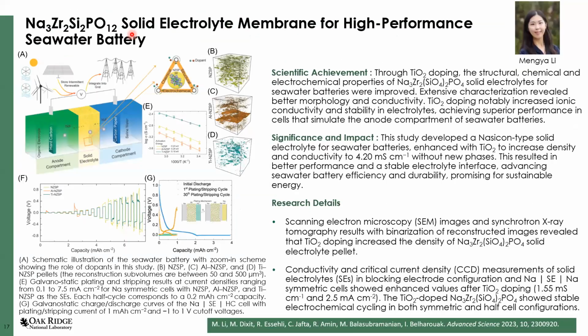So solid state materials are used in other things. In our group, we have small projects on long duration energy storage. This is an example of work where seawater is used on one side of the compartment and an organic electrolyte on the other side. By using this, one can try to make a long duration energy storage device. On the cathode compartment, the reactions that take place are essentially oxygen reduction and oxygen evolution reactions. And on the anode side, it's essentially stripping and plating of sodium, perhaps, or making sodium carbon electrodes where you can put sodium into the carbon and take sodium out of the carbon.